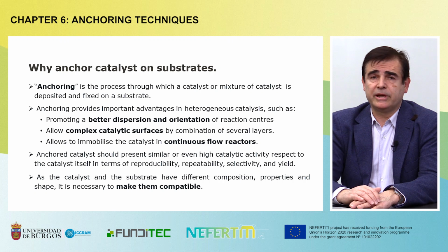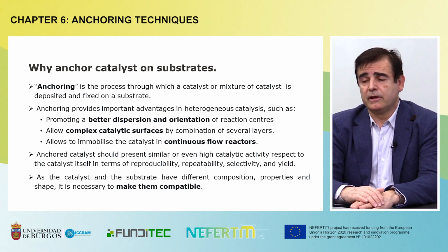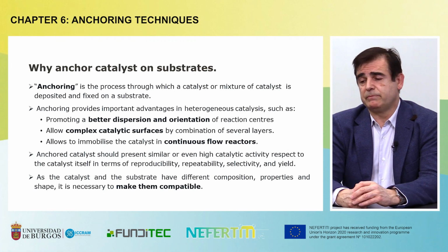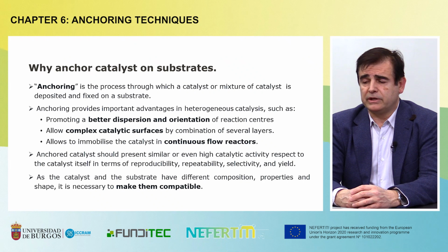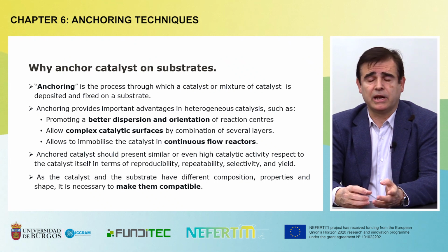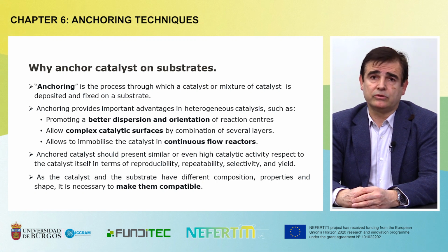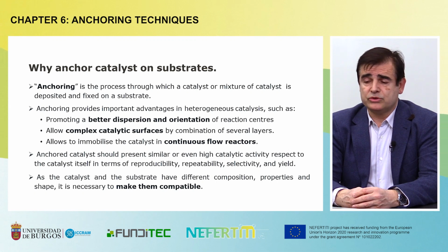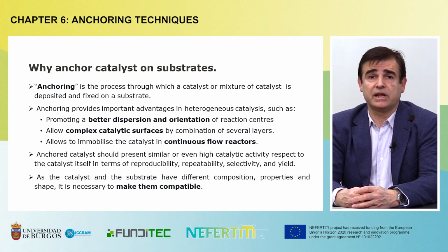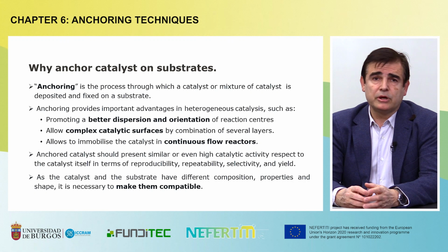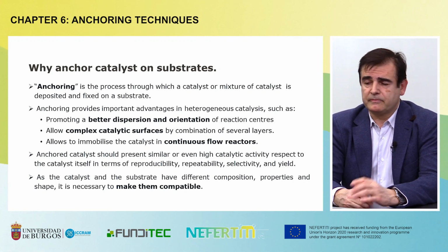Anchoring provides important advantages in the heterogeneous catalysis area, such as promoting a better dispersion and orientation of reaction centers, allowing to construct complex catalytic surfaces by combination of several layers, allowing to immobilize the catalyst in a continuous flow reactor. Anchored catalysts should present similar or even higher catalytic activity with respect to the catalyst itself, in terms of reproducibility, repeatability, selectivity, and yield.